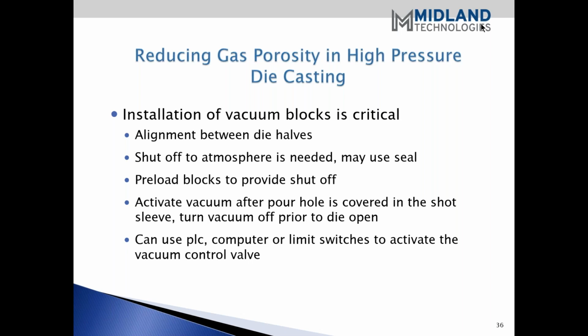Subsequently, the blocks themselves are preloaded, or use seals. I personally have never used a seal in a die, primarily because they are a maintenance item. I know they're used, and I've seen designs with seals. If you have an application that requires sealing and you need a high degree of vacuum, good idea, use them. But in most instances, I have not seen a need for those. Activate the vacuum after you cover the pour hole, and of course it's critical, and then turn the vacuum off prior to opening the die.